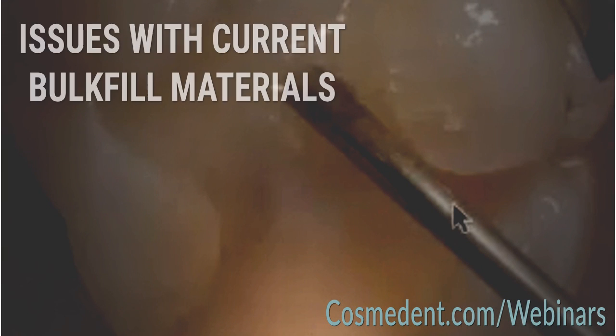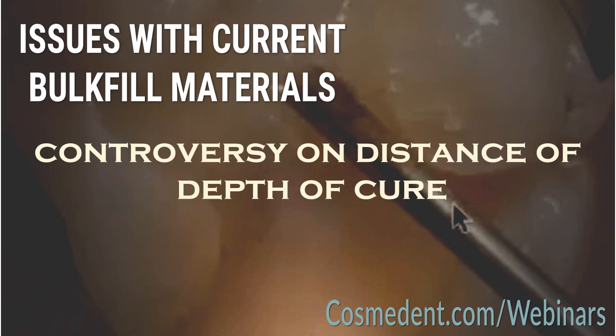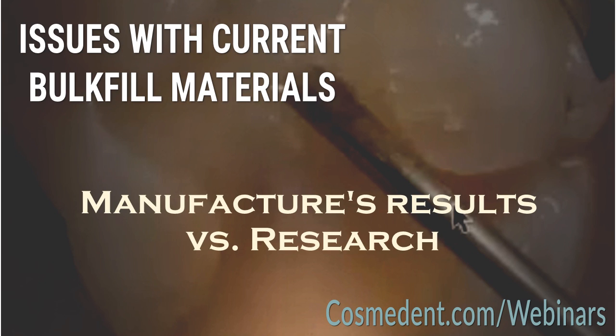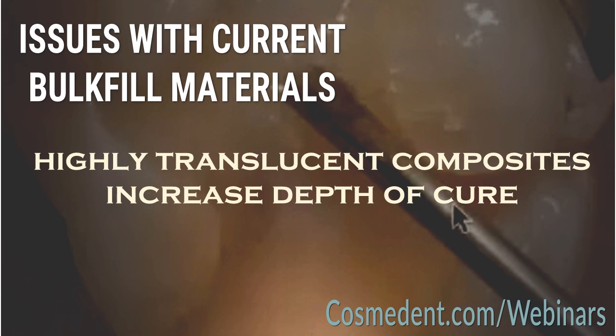So what are my issues with the current bulk fill materials available? Or where do I see some of the problems? Number one, there is some controversy on the actual depth of cure, or the distance of the cure depth with these materials. Sometimes the manufacturer's results on the depth of cure are different and not consistent with what we're seeing in some of the research reports. Also, one of the techniques manufacturers use to create more depth of cure with their material is a more highly translucent composite to help increase that depth of cure. The problem with that is that it can then result in a low value or a grayness of our final restorations,